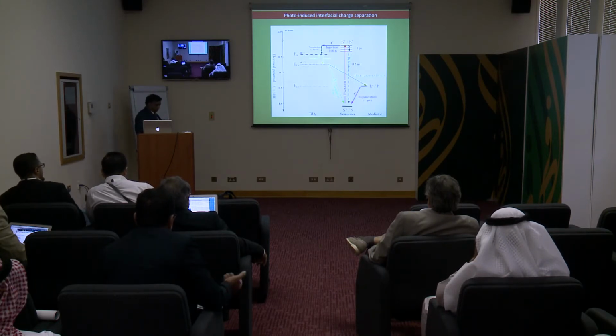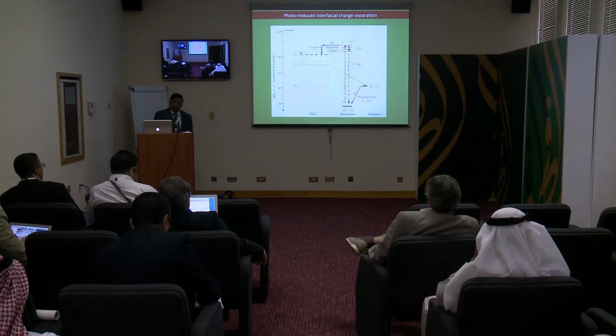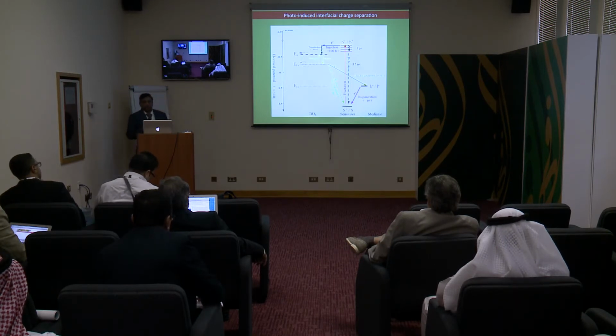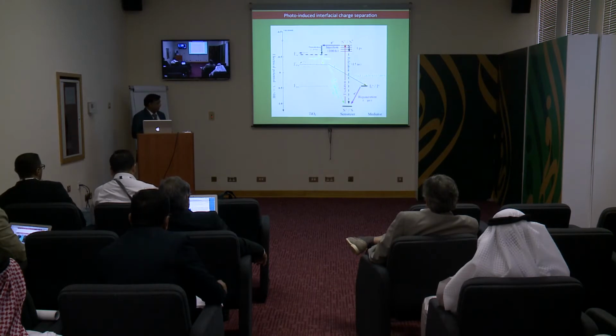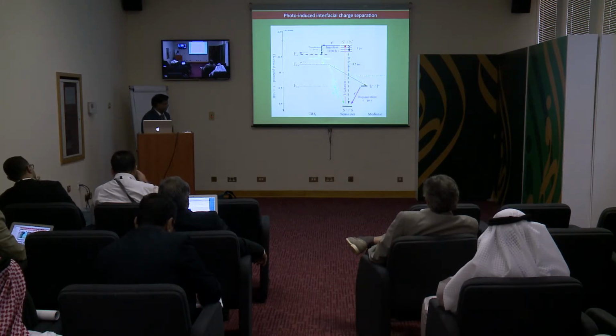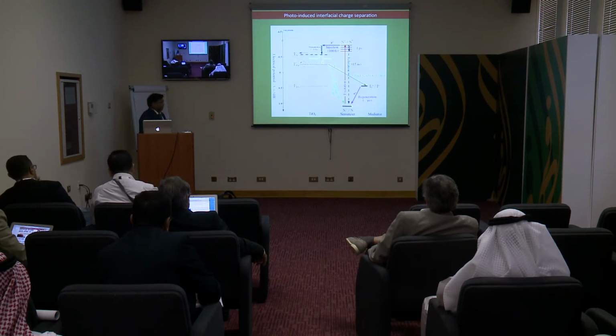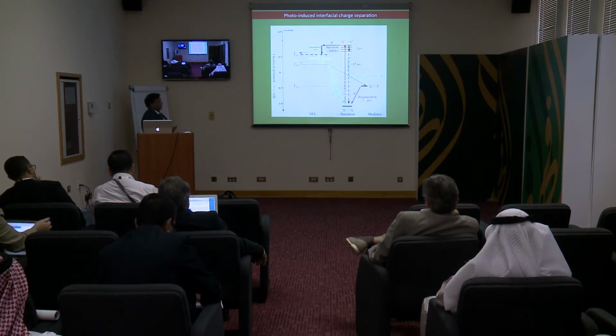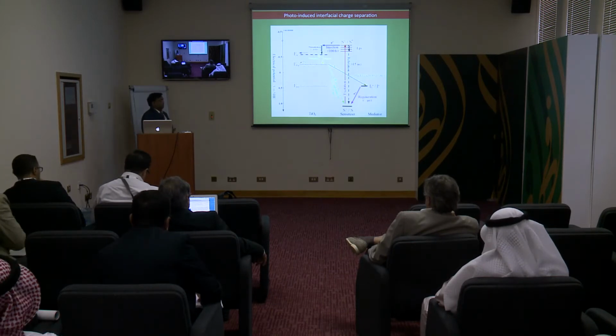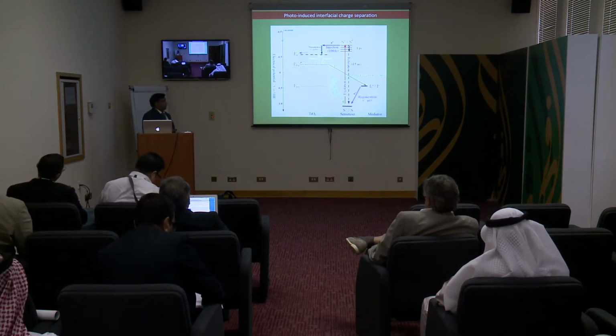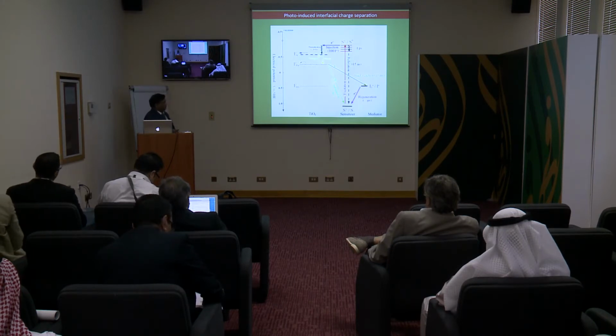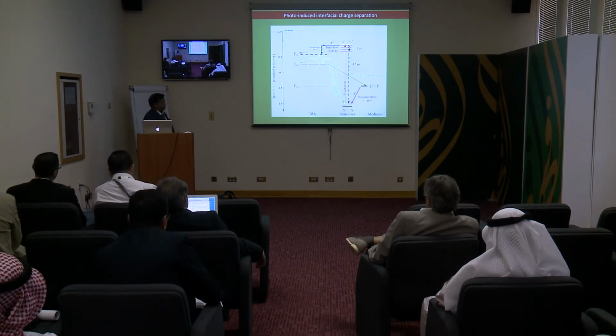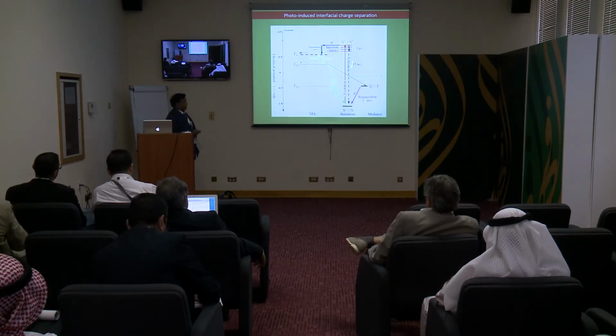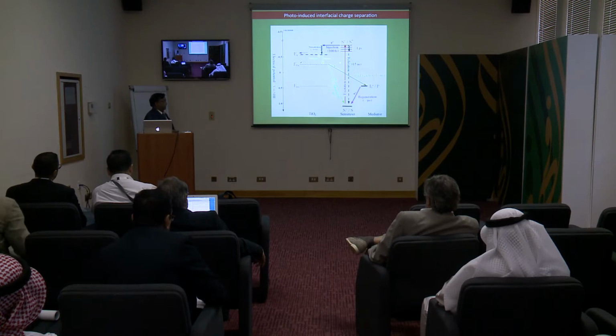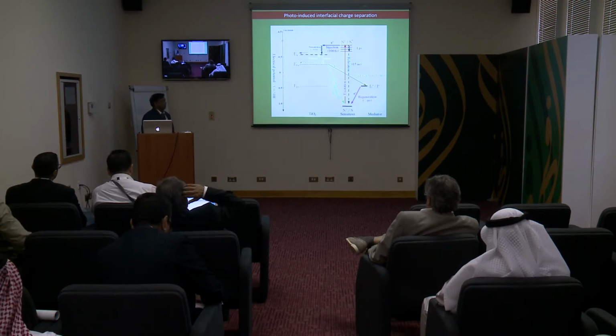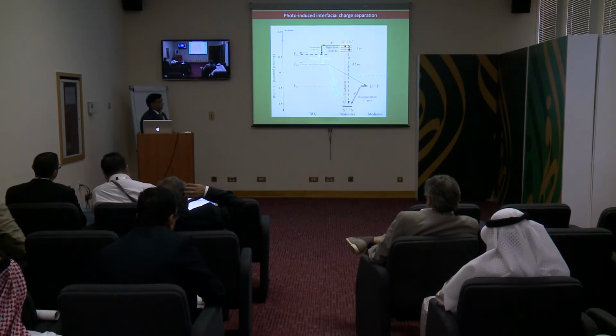As I showed in the earlier slide, this is how the DSC works. It has a competition of different kinetic reactions going on, so let me briefly explain them. Once the dye goes to the excited state, it injects an electron into the TiO2 on a time scale of 100 femtoseconds. Before injecting, the excited dye can also return to the ground state, which has a deactivation period of 50 nanoseconds. This reaction competes with the much faster injection, so no deactivation process is going on.